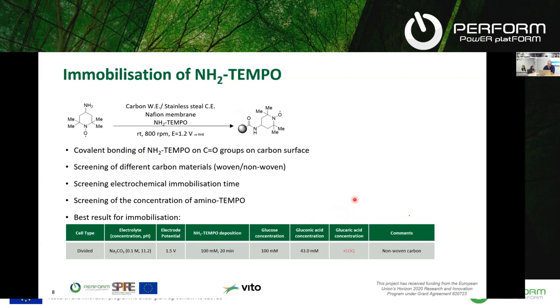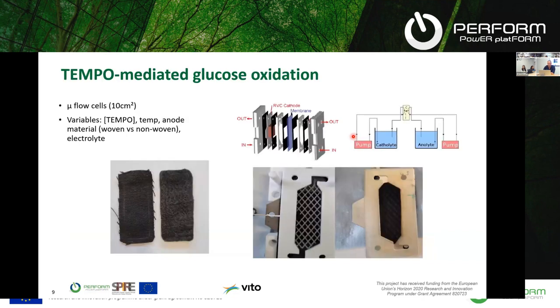So we again were in a situation where we needed to deal with the mediator, so the tempo, which was successful in oxidizing glucose to glucaric acid, but we needed to take care of the downstream processing. We did some additional tests, of course.